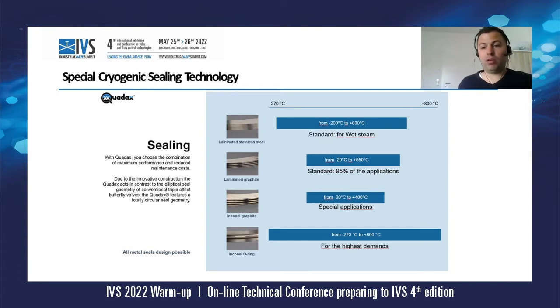We do use the Inconel O-ring. We can go from minus 270 degrees C up to 800 degrees C, and we can work with very high delta T's. We also do have valves installed for liquid helium applications in the aerospace industry, where our valves work perfectly at these very, very low temperatures.